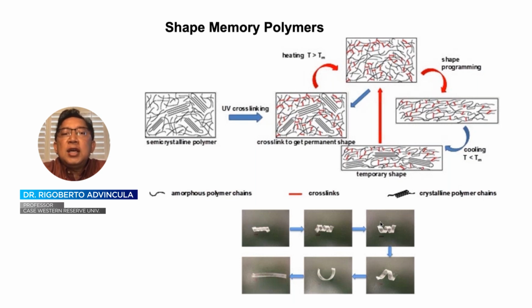The result is you can change the material properties, let's say, by controlling one or two of the phase aspects. In this case, the degree of crystallinity or amorphous transition can be controlled by heating or melting. And then the presence of the cross-link material preserves the shape. Hence, a shape memory essentially is the effect, in this case, of the robustness of a cross-link thermoset or thermoset elastomer. And then the change in shape can be elicited and stimulated by heat, such that the cycle between crystalline to amorphous phases changes in shape.